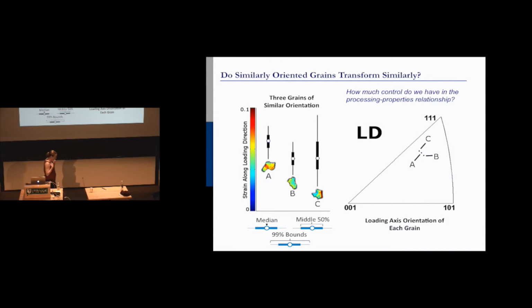And so one of the questions that we were able to look at right away was this assumption that's used in modeling that similarly oriented grains transform similarly. If you have two grains that are both cubic, that are both oriented like this, regardless of their surroundings, the idea is that they will transform the same way. They will have the same amount of transformation. We were able to actually disprove that pretty quickly once we had this data.